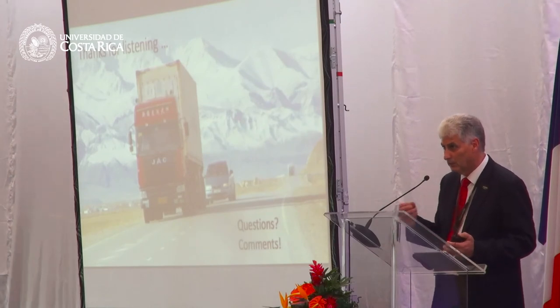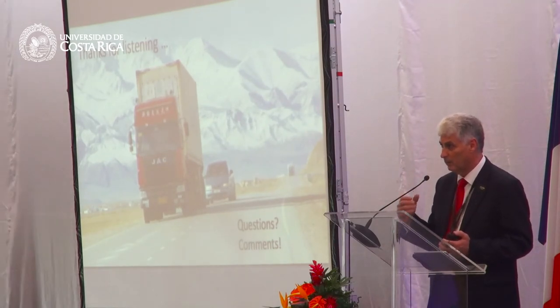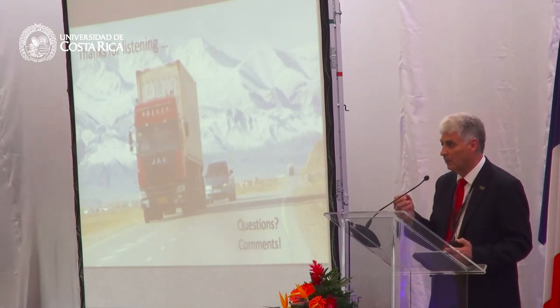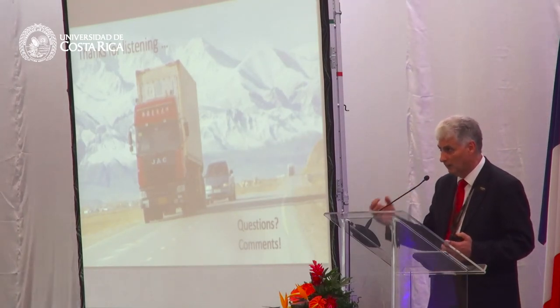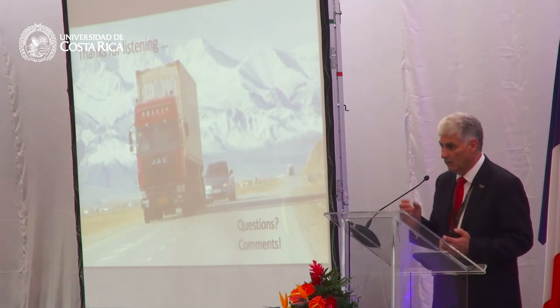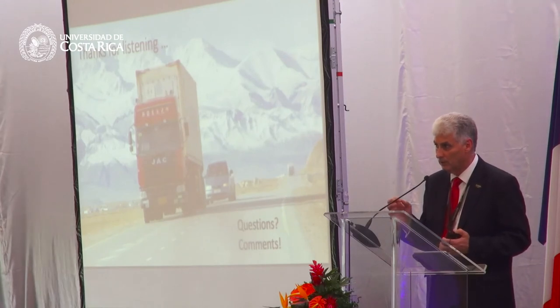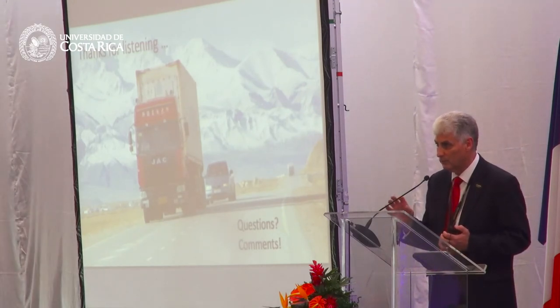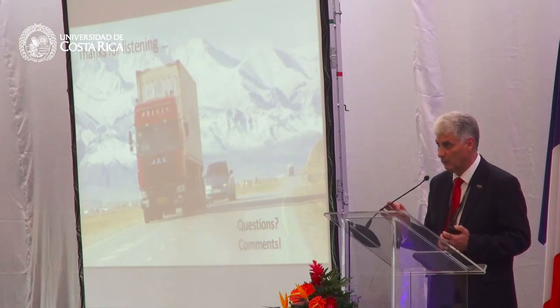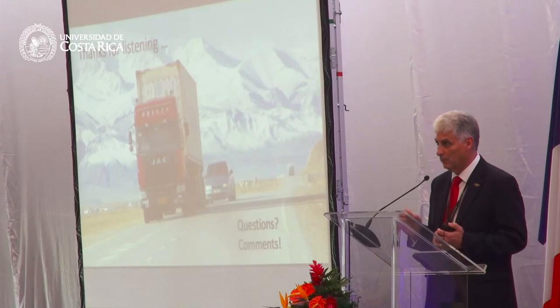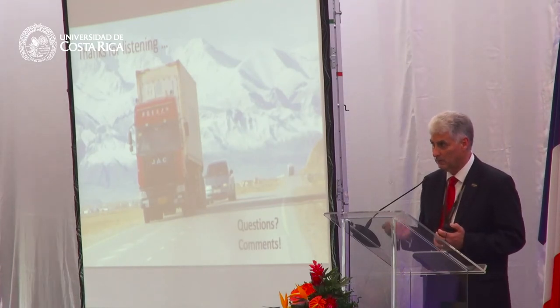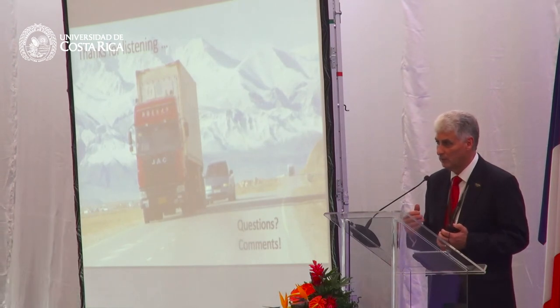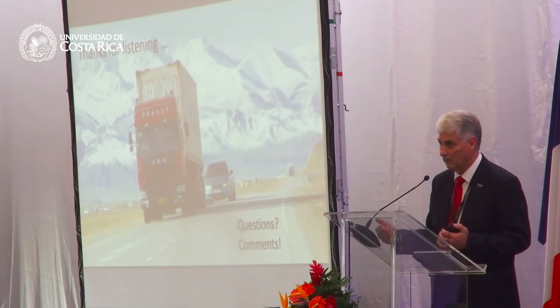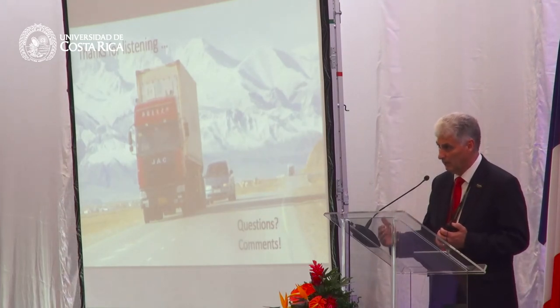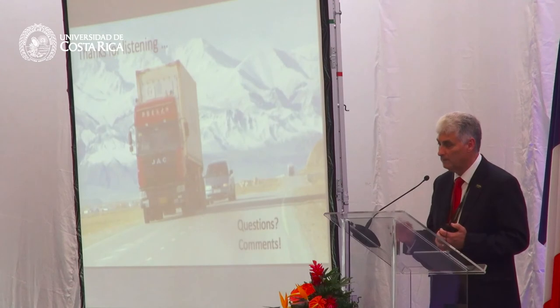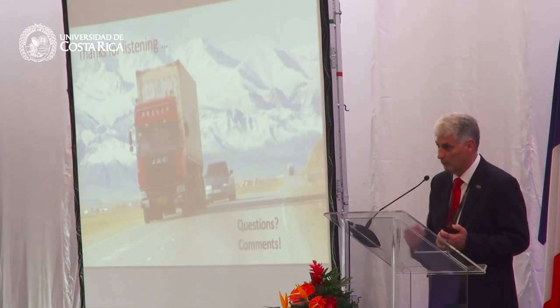Okay, the question is how to qualify the oxidized binder behavior in fatigue and cracking at various temperatures and durability cracking. The fatigue cracking on oxidized binders, I think, is reasonably well captured by the G star sine delta parameter that we have at the moment. If I look at the work done by Mike Anderson at recent expert task group meetings in the US, he's presented a reanalysis of the verification effort. And this is okay for a certain amount of the fatigue that we see. It relates very nicely, the parameter that we have, with the fatigue behavior.